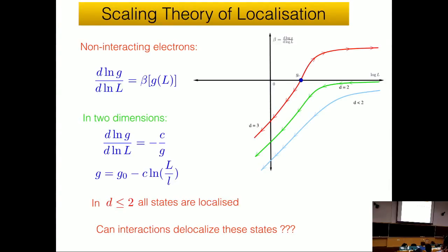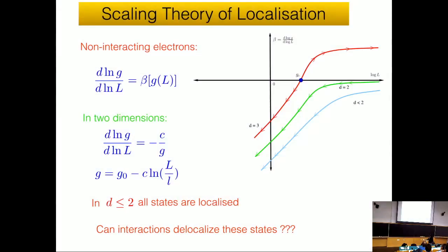So in the limit where the disorder is very strong, you would expect that the states are localized, strong Anderson localized. That means that your wave functions have essentially an exponential spread only, correct? And then what would happen is deep down, right, you should have an insulating state. Now the question is, what would happen to this system as you keep increasing the system size?